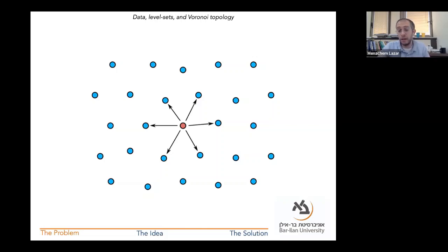The angles maybe are not exactly all 60 degrees, so the variance now is some positive number. And the idea would be, well, maybe the smaller that variance in the angles, the more crystal-like it is, and the higher it is, maybe we should say, well, I guess we must be nearby a defect. Okay, so that's one idea.